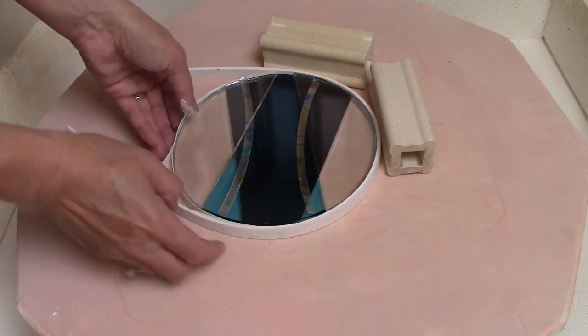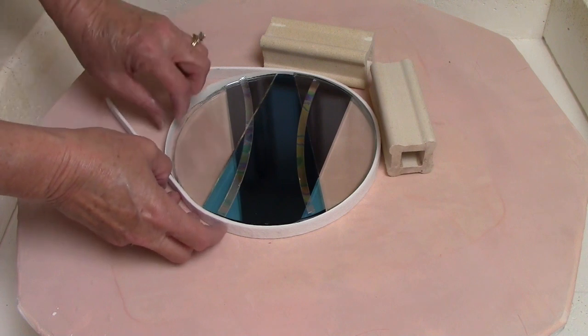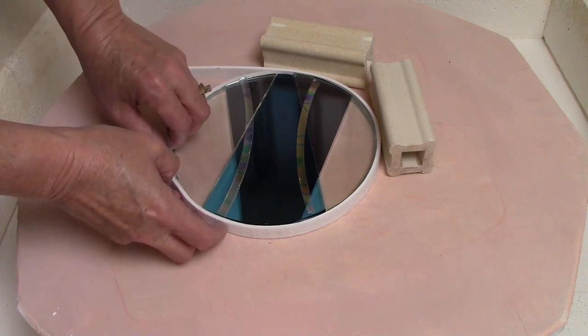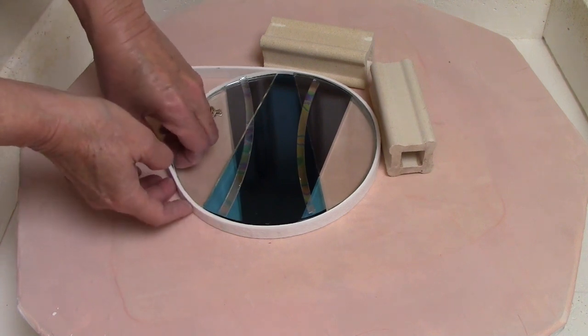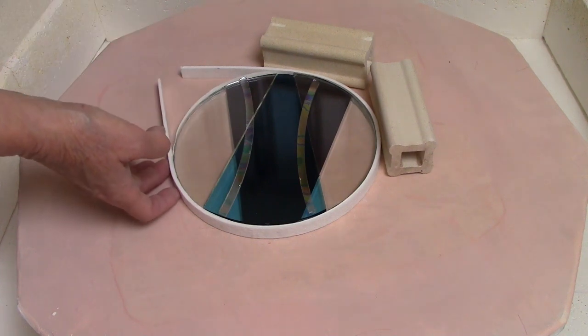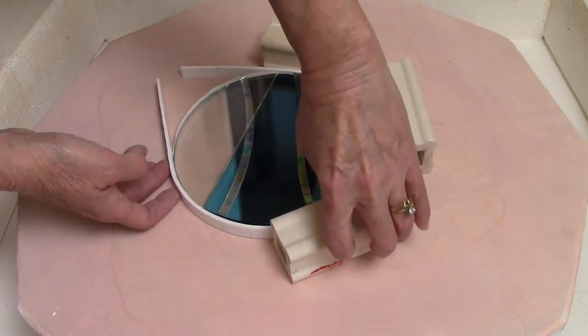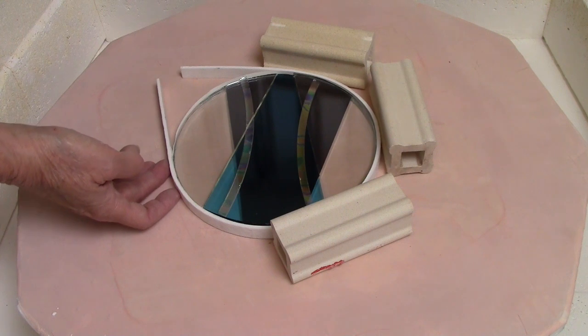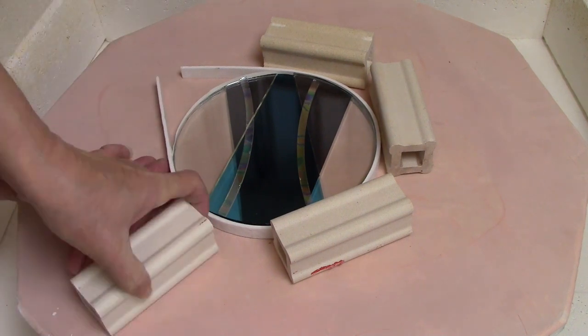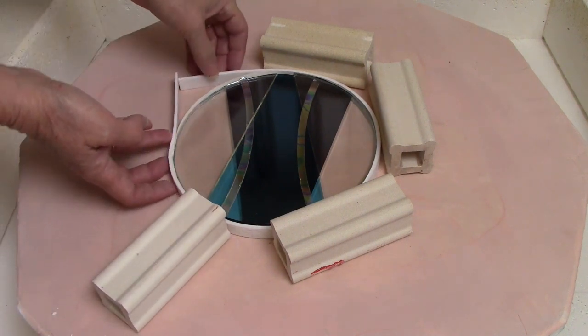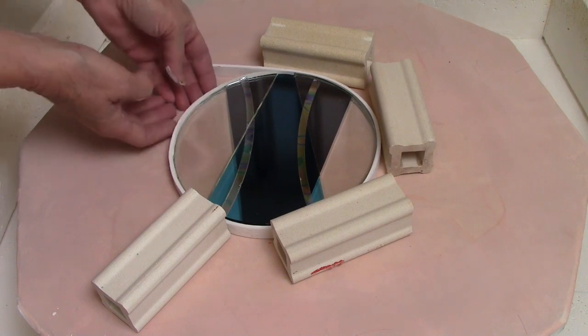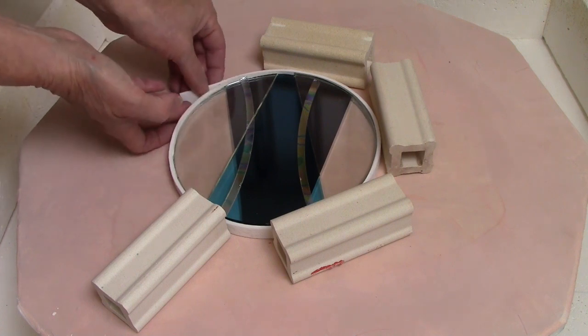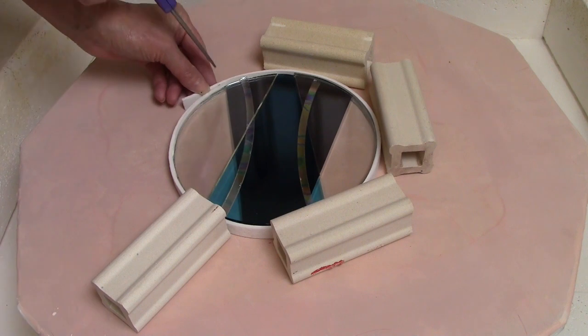When firing thick glass like this, we have to contain it in order to retain that size and shape that we want. Now this is about a 7-inch circle. So in order to retain that 7-inch circle, I'm wrapping the glass with a piece of thin fiber paper and then a piece of 1/8 inch thick fiber paper. And we're surrounding that with kiln posts in order to contain this glass to retain the shape and the thickness of the blank that we're creating.